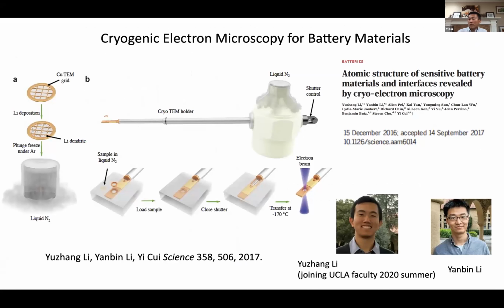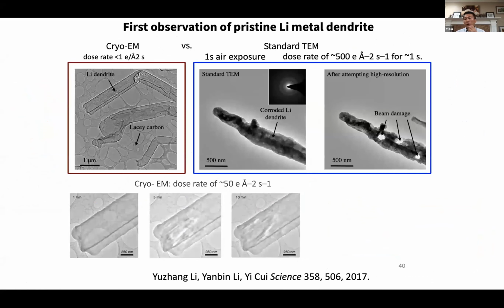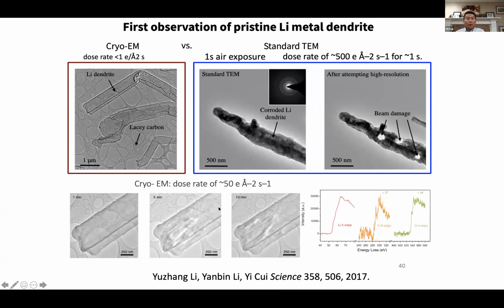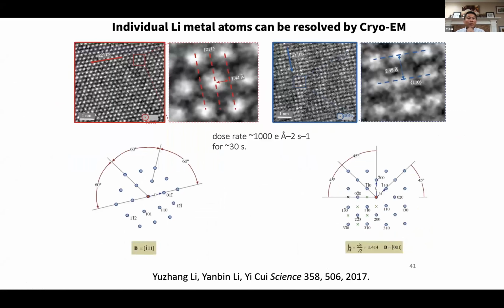I talked to my student, I said, this could be used for our battery research, back in 2016. And we developed a methodology of cryo deposition and then plunge freeze and doing the cryo transfer without exposing to the air into the TEM, to stabilize the sample. And this allows us for the first time to really obtain very exciting information. For example, this lithium metal dendrite is stable inside TEM under the beam for quite a long time, it turned out, compared to the biomolecule. It's metallic lithium. And for the first time we obtained atomic scale resolution of lithium metal.